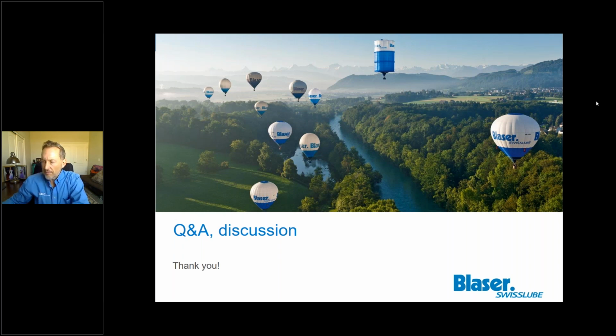The first question was from Kevin. He wants to know, what is better, DI or RO? We switched to RO when we went to full synthetic. Good question. When it comes to the quality needed for metalworking fluids, DI water and RO water provide good enough quality that's required. Some customers who have really bad water will have an RO system, and then they'll take the RO water and put it through a DI tank, just to be sure, because their water is so poor. But most customers can use either RO or DI and have really good results with your cutting fluid. Just make sure it's monitored and make sure the water quality is consistent.